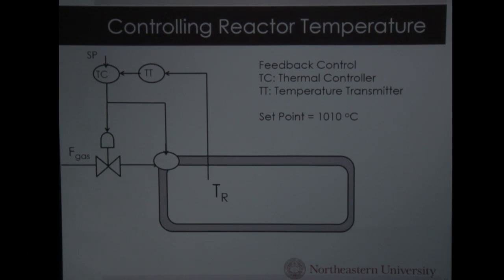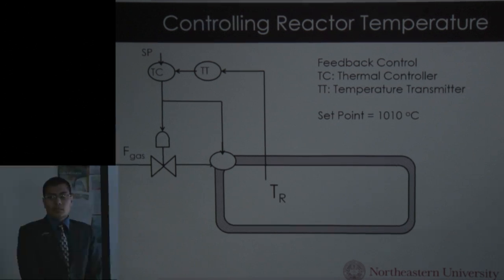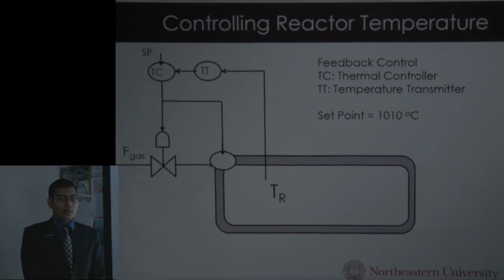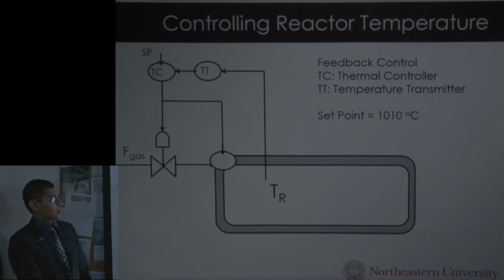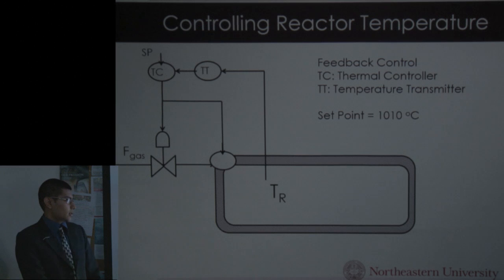Okay. So in the tube furnace, there is a range of temperatures available from between 800 degrees Celsius to 1200 degrees Celsius. However, for our optimal reaction conditions, it's better to have it around 1000 to 1010 degrees Celsius. Thus, to regulate the temperature, we have a temperature controller, which is controlled by a feedback controller that contains a thermal controller and a temperature transmitter. Here, once we set the temperature at 1010 degrees Celsius, once the temperature of the furnace goes above the set point, the valve over here closes so that the temperature comes down to the normal required temperature. In case the temperature goes below, then the valve is opened to heat up the system to bring it back to the set point.